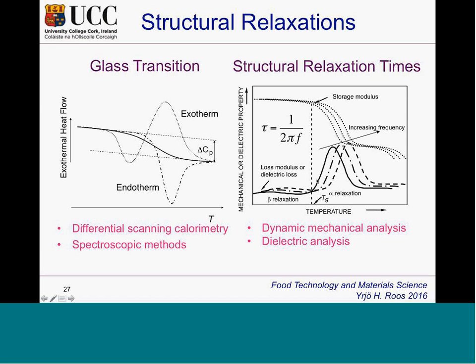If we look at the loss modulus, this means when the material is able to have external heat generation, so slow frequencies are closer to the glass transition than high frequencies. So we can identify where this loss modulus peak is, and we use that as a temperature value. We could also say that our relaxation time is related to the frequency, and we could see how the relaxation time and temperature above the glass transition match each other.